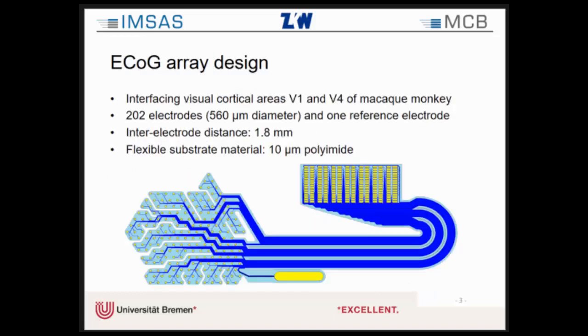So I would like to show you the design of our ECoG array. The design was made for interfacing the visual cortical areas of V1 and V4 of the macaque monkey. In total, we now have 202 electrodes, each of a diameter of 560 micrometer, and also an integrated additional reference electrode, which will be flipped to the backside to achieve a skull-facing reference. The inter-electrode distance of the electrodes is 1.8 millimeter, and as a flexible substrate, we use polyimide, which is mechanically stable and also proved to be stable in saline condition.